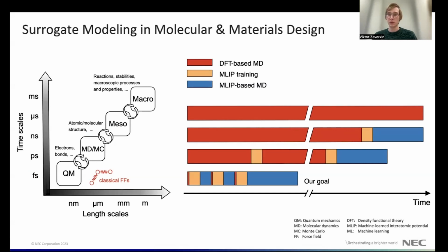And this can be quite computationally expensive because this often means evaluating energies and forces for a large number of atomic configurations. Machine learning helps us to reduce this computational cost by allowing us to learn surrogates from explorative simulations run for shorter time and smaller systems. Here, explorative simulation means a simulation run to explore the phase space of the atomic system we are investigating. We can improve the computational efficiency of the data generation and surrogate training by using active learning, which iteratively improves our surrogate here.